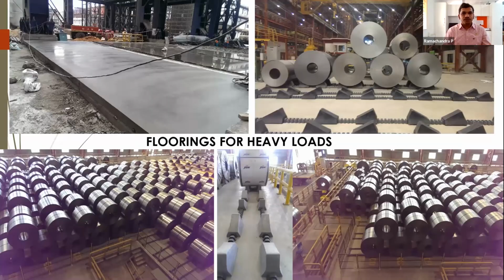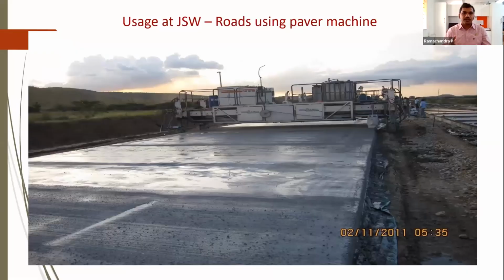Here we can use flooring for heavy loads. One author has published a paper on GGBS, so we can use GGBS in flooring for heavy loads. We can also use steel slag in paver roads. This fine aggregate, obtained from the steel industry, ground granulated blast furnace slag as a fine aggregate, has been effectively used, and it has been implemented in the code also.